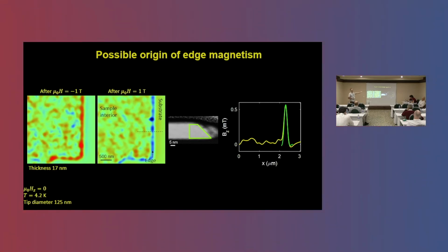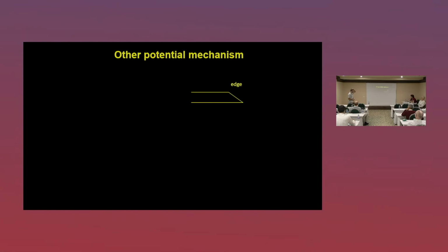There are a lot of things that happen at the edge. There are dangling bonds and unsatisfied bonds, and that could also be the case. And if you think that, you might be referee number 2. But we thought about it for quite a while until we realized that there are other edges. So this is an edge, but there are also step edges between two terraces. At this step edge, you have the same dangling bonds as in an edge. But if you're above the critical thickness, you should not see anything.